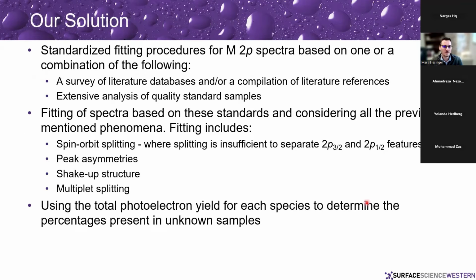And so we've gone to a process where we do standardized fitting procedures for the metal 2p spectra, based on generally extensive analysis of quality standard samples. And then we look at those standard samples and we curve fit based on the fact that there should be spin orbit splitting. If the splitting is not sufficient to separate out the 2p3/2 and 2p1/2 features for all the different species present, we take that into account.